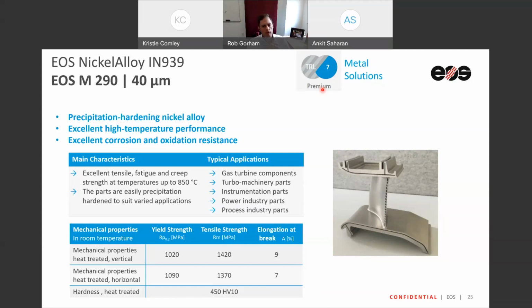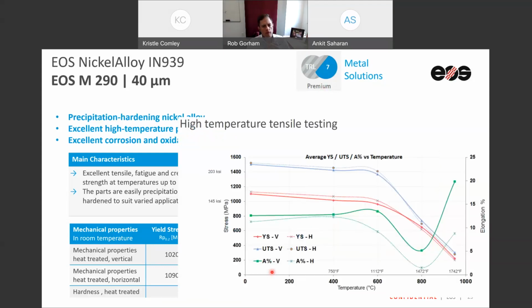So it's not only the mechanical data that matters, like I said, in this case, high temperature tensile testing also matters. So you can actually see that the material is pretty stable, almost up to 600 Celsius, which is about 1100 Fahrenheit, before it drops in strength and goes from there.